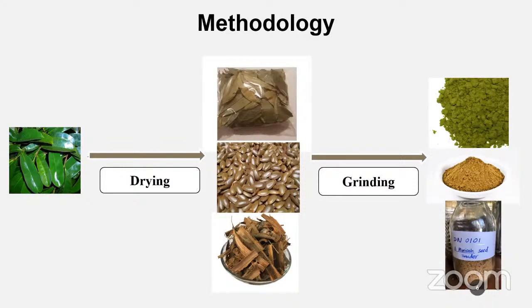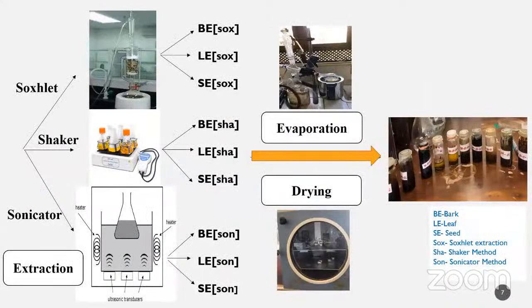After that, the three materials were extracted using three different extraction methods: Soxhlet extraction, shake extraction, and sonicate extraction. Here methanol was used as the solvent. Finally, the extracts were evaporated to remove excess solvent using the rotary evaporator and dried well in a vacuum oven. Then we obtained crude extract samples.